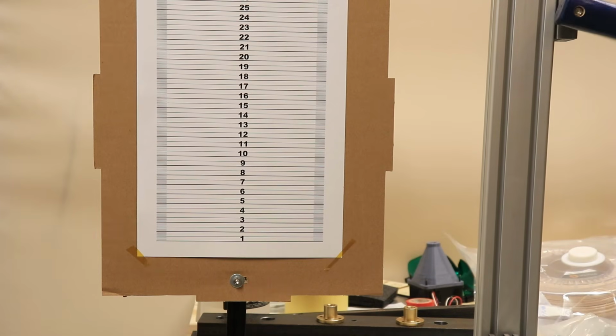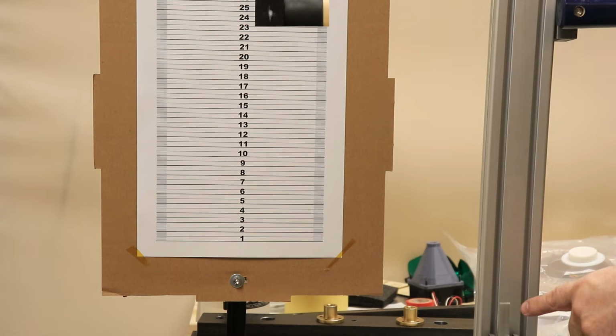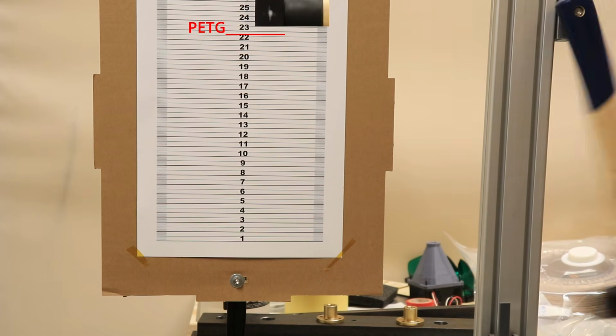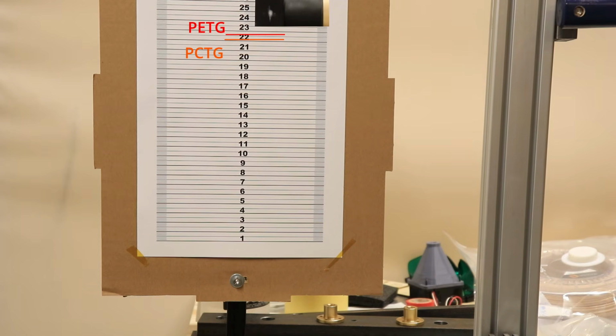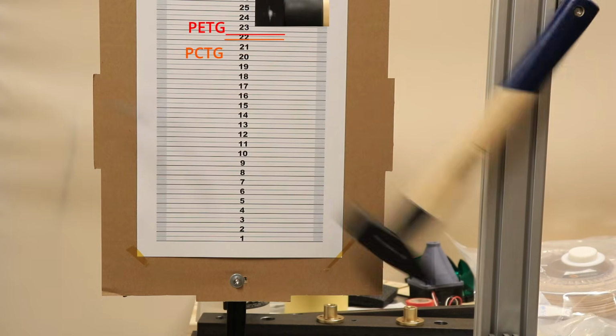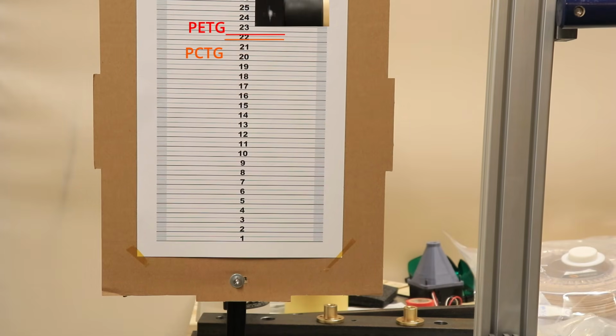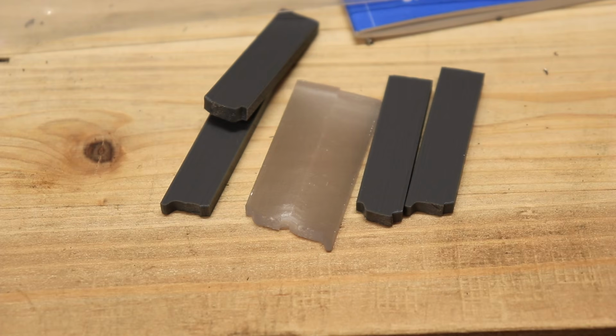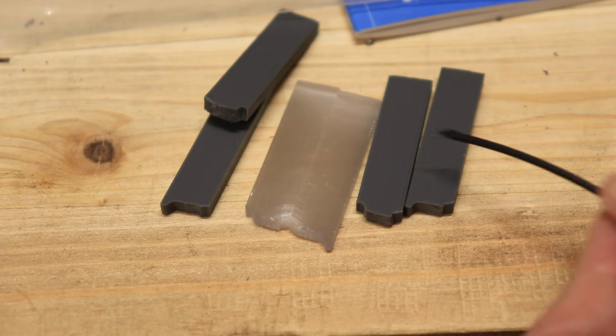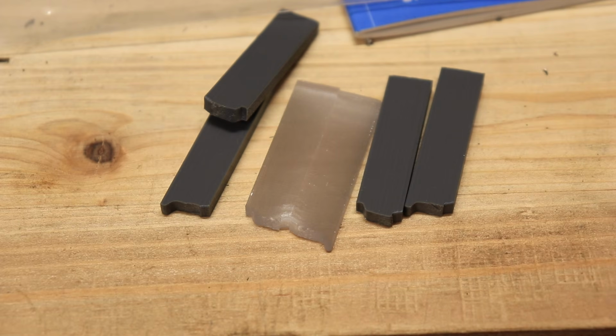0 position. PETG, PCTG, PCTG second time. Well, I don't know the numbers yet, but I'm a little bit disappointed with PCTG because if it had a strength of 90 kilojoules per square meter, it wouldn't break under a half kilogram hammer in this test.